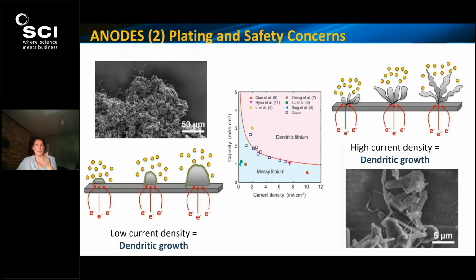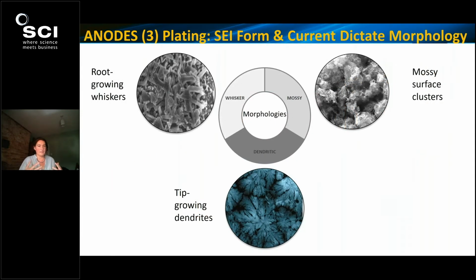Now, in a worst case scenario, when these are able to penetrate the organic or the insulating separator, they can cause a short circuit, which can be quite hazardous in lithium-ion batteries. But generally, any kind of plating is not overly problematic, other than it depletes capacity because it uses up lithium that you can't then get back. But in a broader sense, because we have obviously a number of different current densities depending on the cell type, whether it's an energy or a power cell, you can get very different types of plating morphology, but they are typically categorized as mossy, dendritic, or more whisker-like in between.